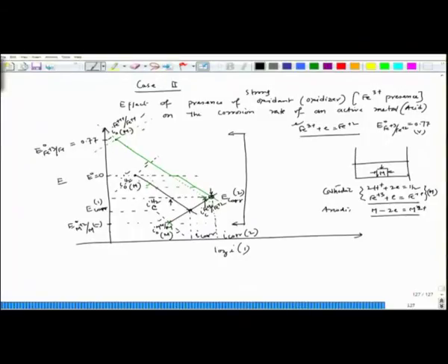At this point I could see that I_A equal to I corr equal to I_C, and this I_C is basically the addition of I_C(H2) plus I_C(Fe+3 to Fe+2) at E equal to E corr 2, condition 2. So we could see that again the corrosion rate of the metal is going up, and since it is in log scale, this corrosion rate increment of that metal is very high.